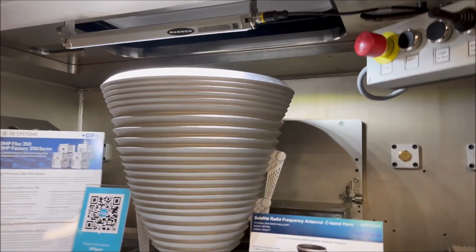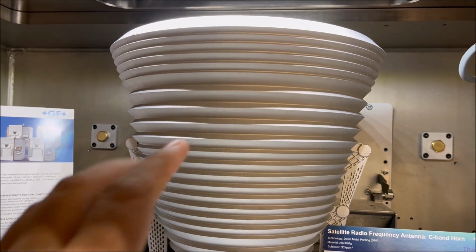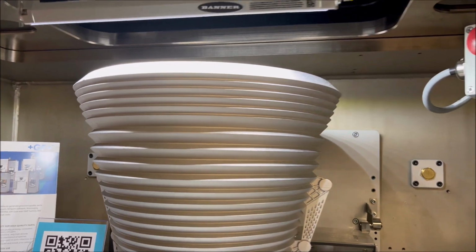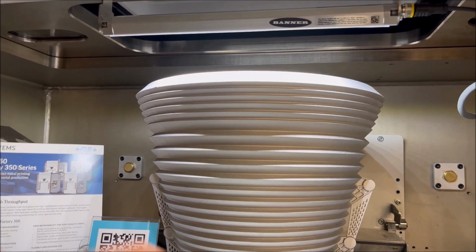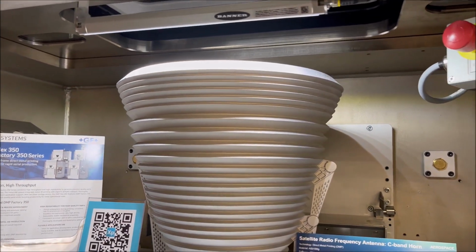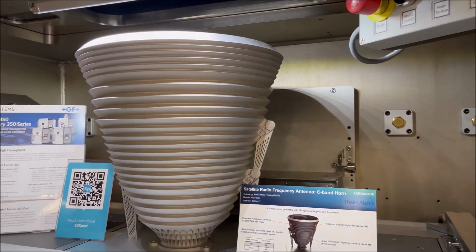So the beauty is you get seamless parts. This is a completely seamless part. The left and right lasers do the infills, whereas the central one does the borders. Now this is extremely important in aerospace. So we have other OEMs that have multiple laser systems, but some of them are quad based. So quad based meaning you'll have stitch lines on these large parts. And now, as you know, for aerospace, a stitch line is a very bad thing. But in this case, you can see this is a completely seamless part. There's no stitch line at all. And that's the benefit of the triple laser system.